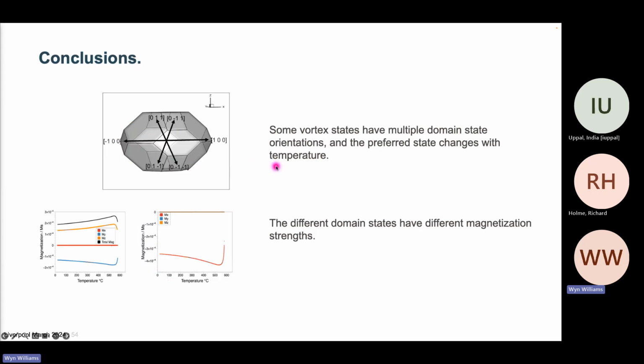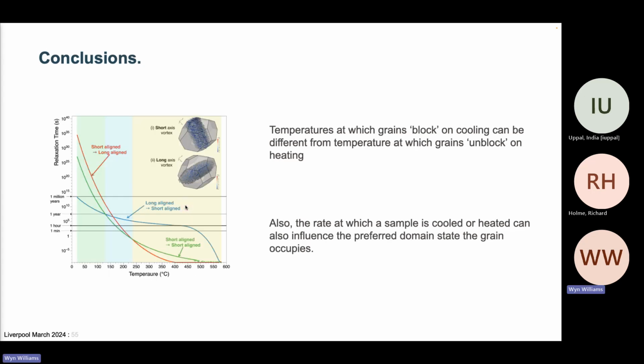The problem is that sometimes in some types of grains the replaying of this magnetization causes problems because of the difference in cooling rates and because of the difference in the availability of domain states at different temperatures. That affects certain vortex states. It doesn't affect them all, otherwise none of your paleomagnetic samples would ever work. The question is which ones of them are likely to be more affected than the others, and probably Greg and Les have a good idea of why. I think I do too.